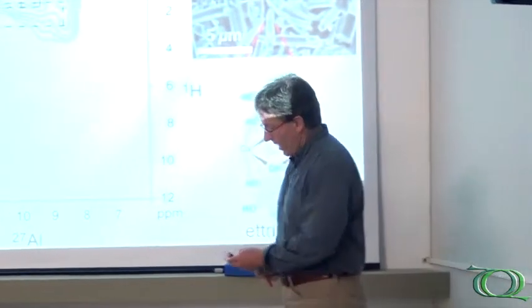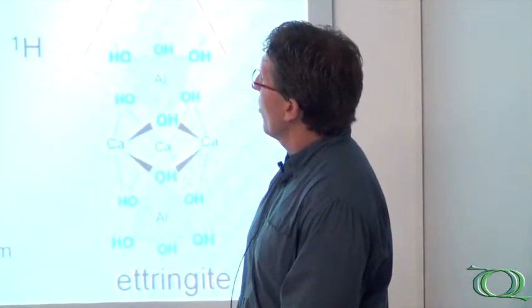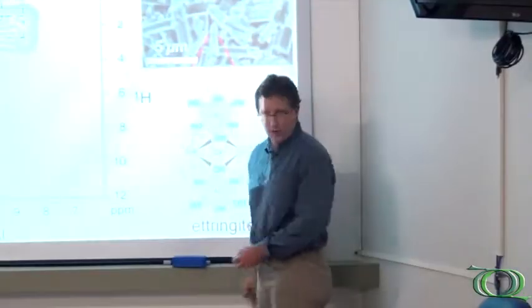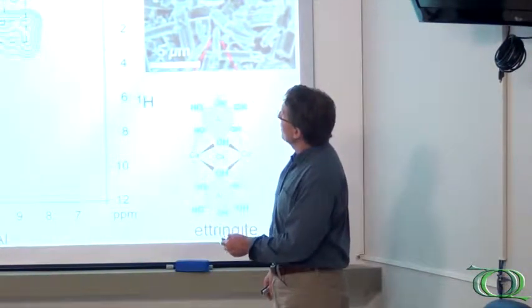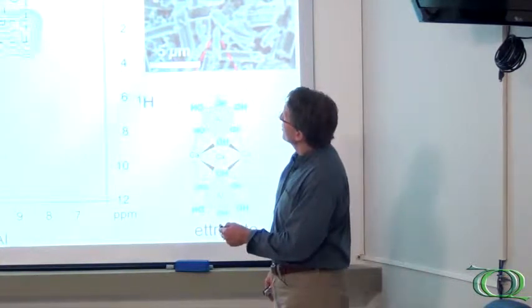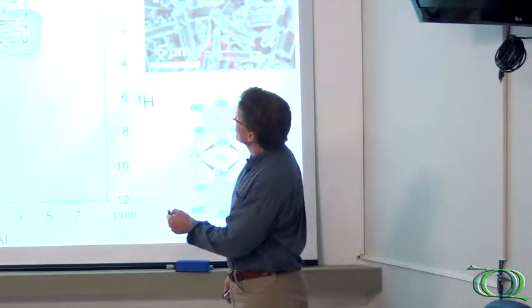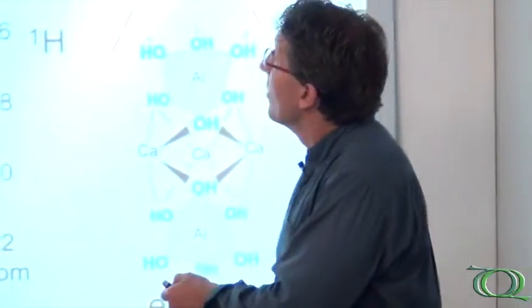And now we see that these broad signals are actually comprised of some very specific signals from very well-resolved species in the two-dimensional frequencies. So we've done these in Santa Barbara, we have an 800 megahertz instrument, so it's 19 tesla, and using these conditions, we can get beautifully resolved signals, which now we can attribute to ettringite, which is one of the major crystalline components in cement. This is ettringite, these are the crystals I've talked to you about, they're aluminate hydrates, these long needle-like aluminate hydrates, monosulfate, and a few others, such as these octahydrates and hexahydrate species, which yield very distinct aluminum NMR signals, which now gives us great ability to then quantify, resolve and quantify these in a way which gives us unprecedented insight on what the nature of the cement chemistry is. Just no one had applied these very powerful two-dimensional type methods to these complicated mixtures before us, and we were motivated and been working with the cement community in order to choose conditions which made it relevant.